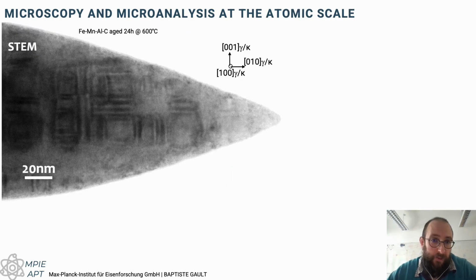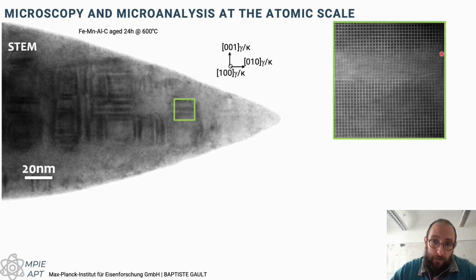A key strength of MPIE has been the development of infrastructure and methods to complement measurements obtained from transmission electron microscopy. In this case, for example, scanning transmission electron microscopy through an atom probe specimen, in which we can see contrast pertaining to precipitates strengthening this austenitic steel, and we can perform high resolution, high angle annular dark field STEM on these samples. We can image the organization of the atoms here, for example, inside of one of the strengthening precipitates. And in the matrix, we can see that the organization of the atoms is different.